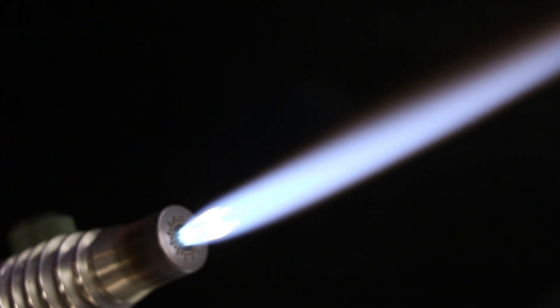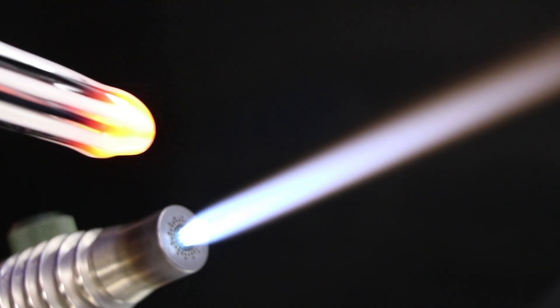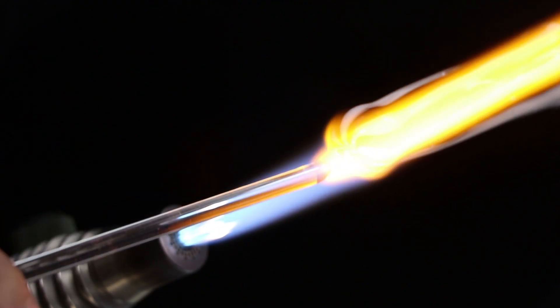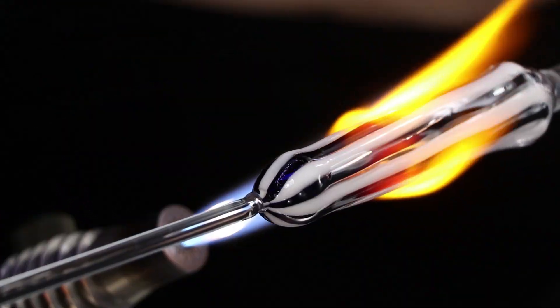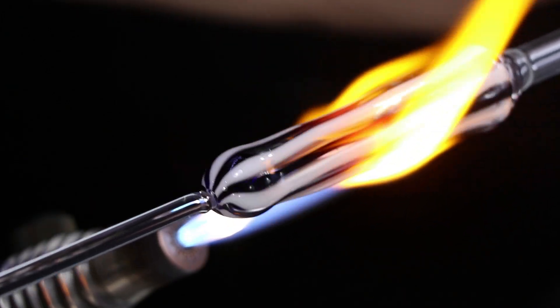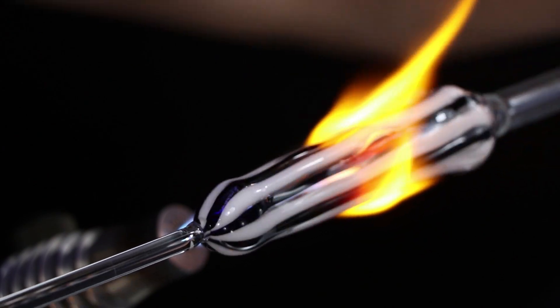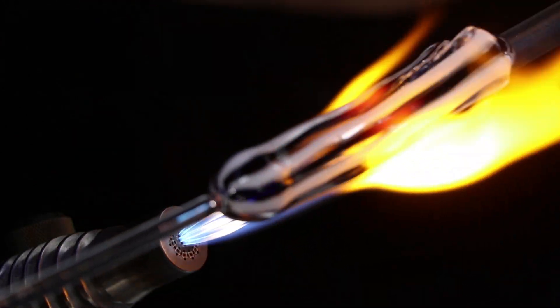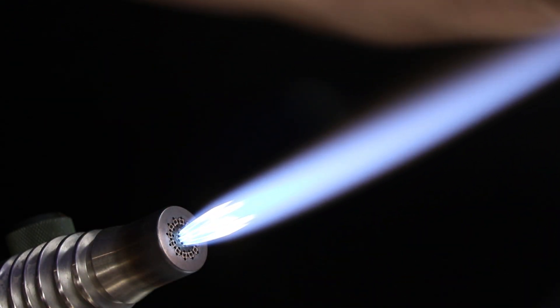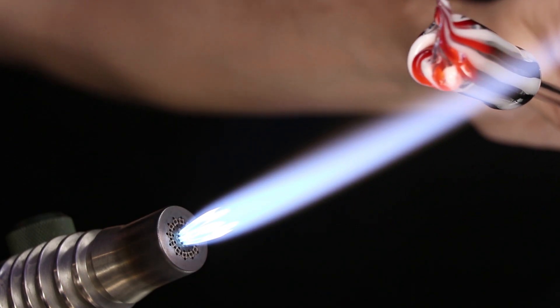Sometimes they say it's not what you can make, but what you can save. So I went ahead and blew that air bubble all the way to the end so it's nice and even and I can open it up to make a tube. But before that I'm going to try to get some of these cracks melted out — I had a couple come down from the blow tube where it was a line of clear in between the lines. It's cracking on me a little bit more still; I should probably be using the kiln. I think I'm going to have to flame cut it again and use just this smaller section, and get rid of the one that was cracking up on me.